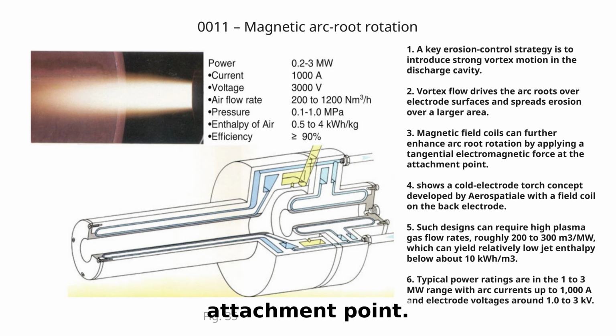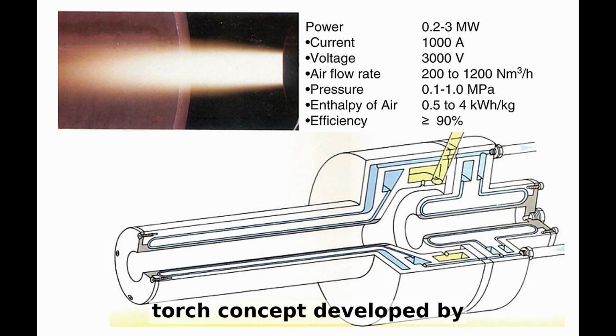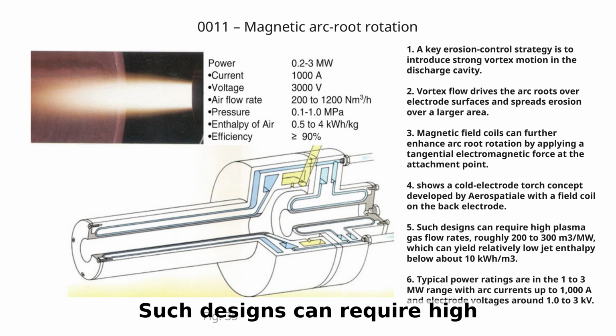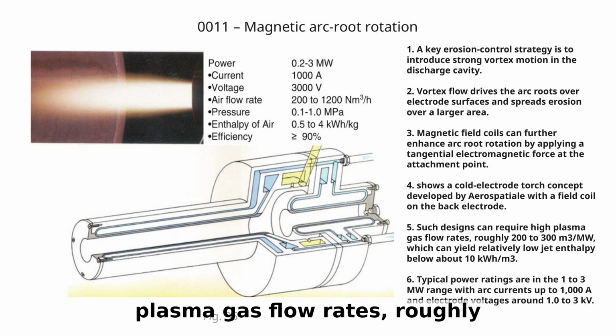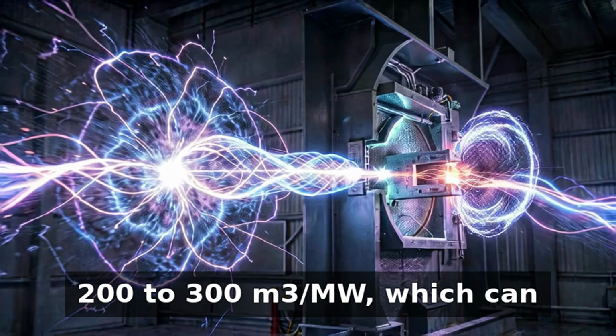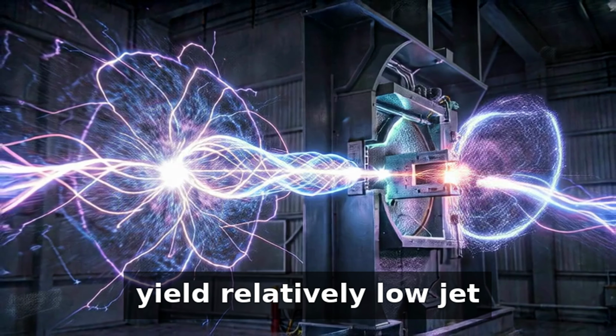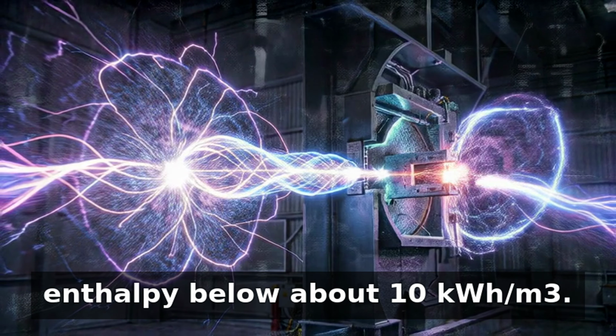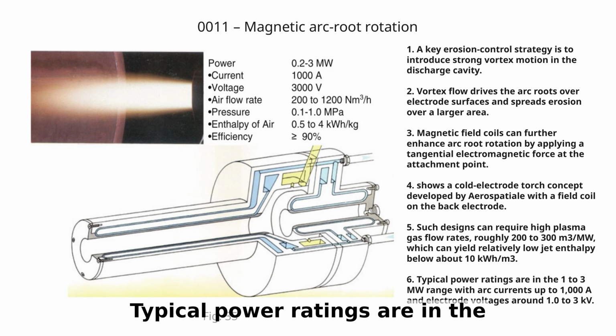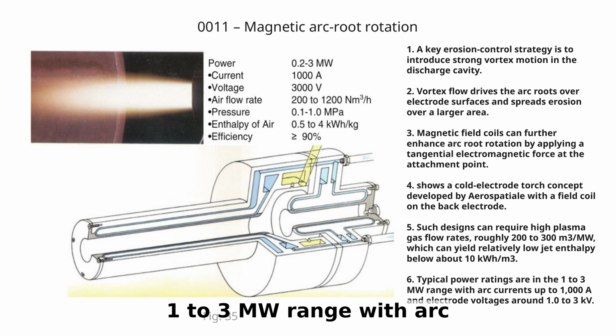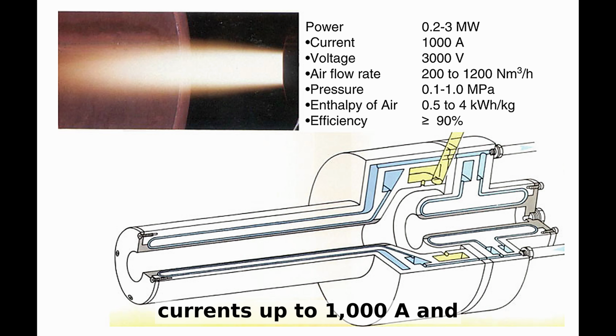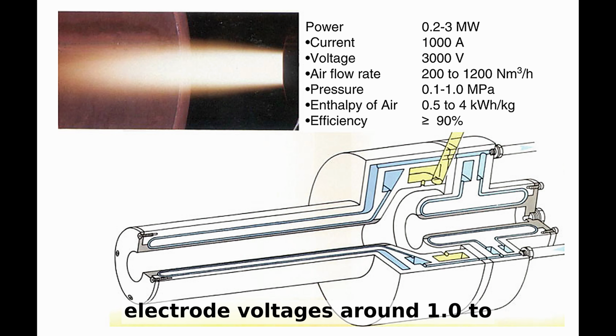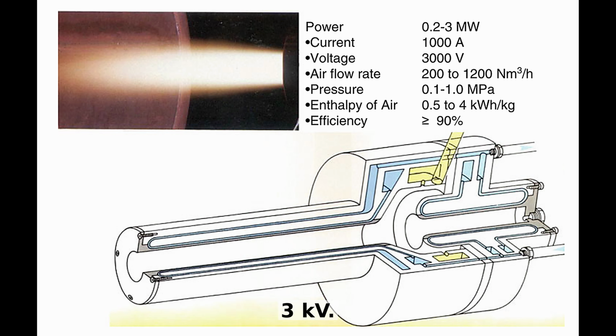Figure 35 shows a cold electrode torch concept developed by Aerospatiale with a field coil on the back electrode. Such designs can require high plasma gas flow rates, roughly 200 to 300 cubic meters per megawatt, which can yield relatively low jet enthalpy below about 10 kilowatt-hours per cubic meter. Typical power ratings are in the 1 to 3 megawatts range with arc currents up to 1000 A and electrode voltages around 1.0 to 3 kilovolts.